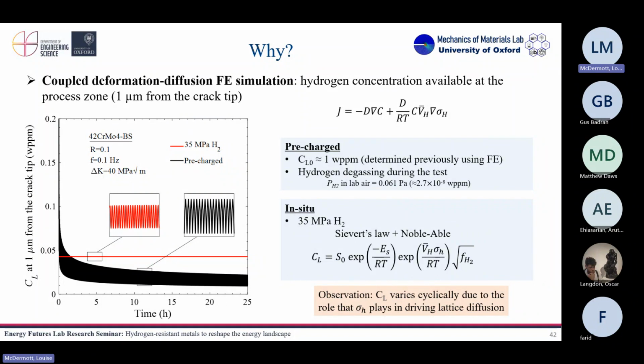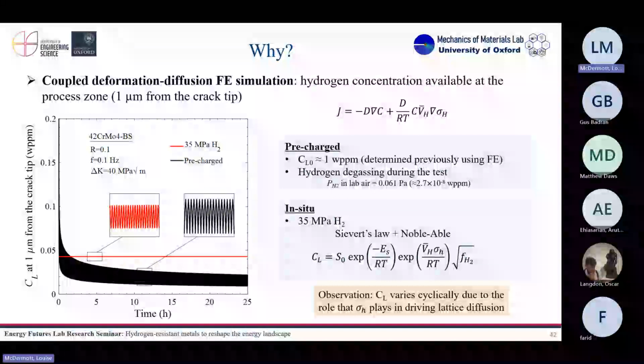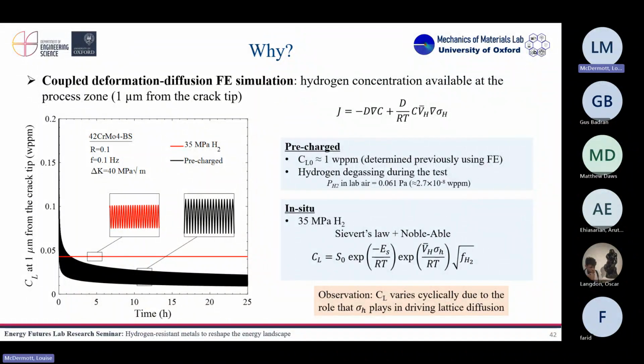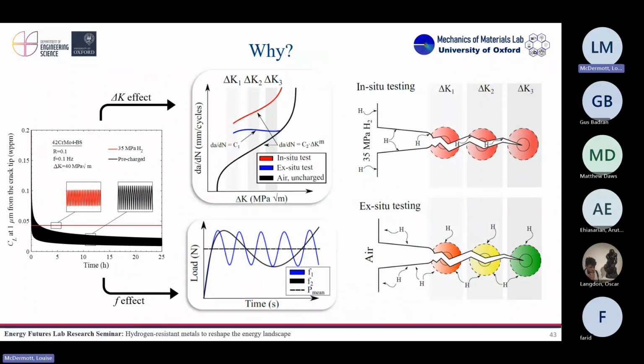If we have a look at the samples that were tested in a hydrogen atmosphere, the hydrogen content at the crack tip was pretty constant along the whole experiment, while the samples that were pre-charged first and then tested in air had this behavior. So we saw that the hydrogen was very big at the beginning, but pretty soon after we started the experiment, the hydrogen concentration dropped below the hydrogen concentration in the samples tested in the hydrogen gas atmosphere. So okay, this can actually explain, and I'm going to go to the next slide, why we have this flat region here.